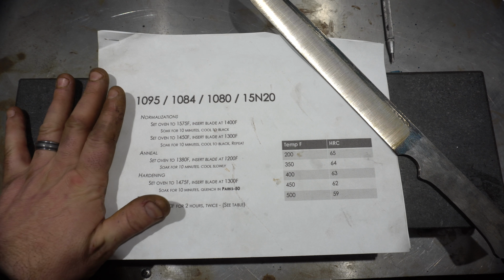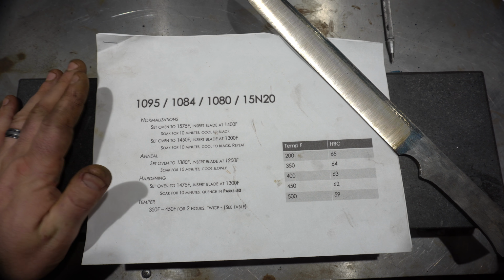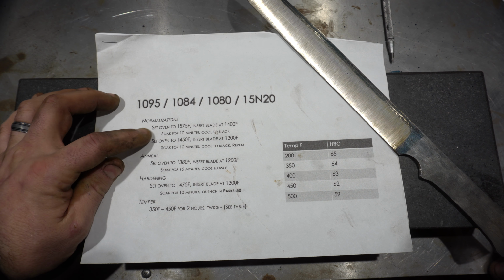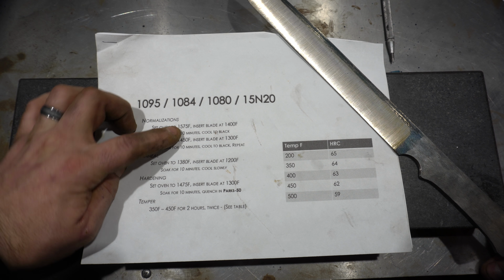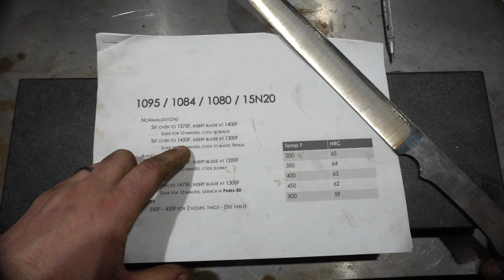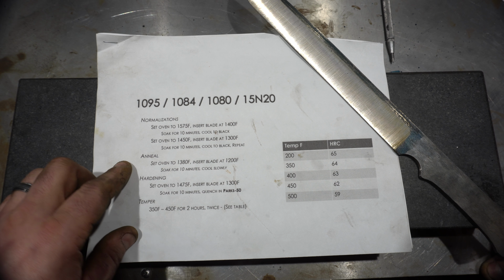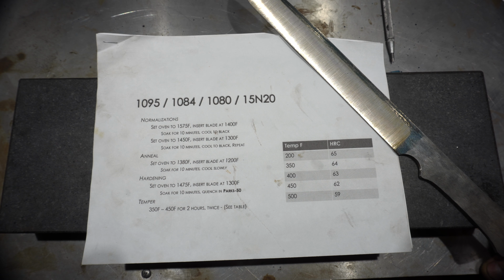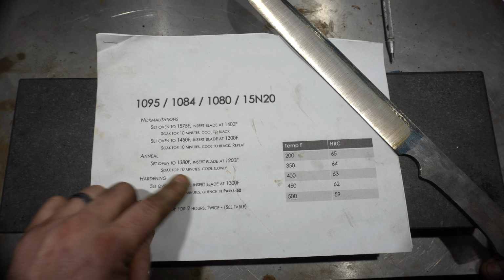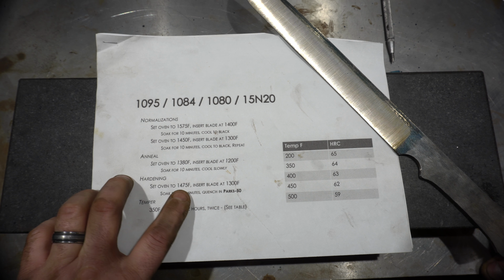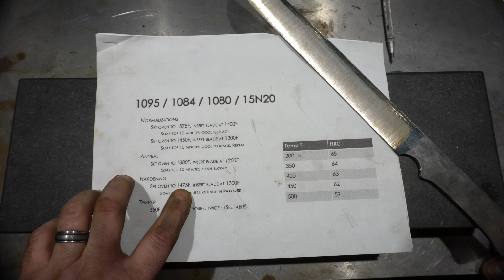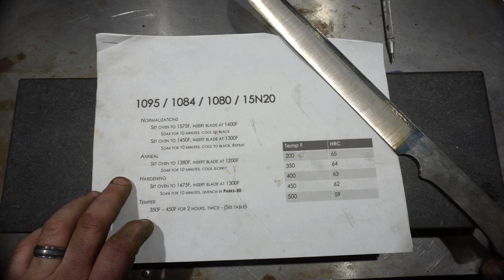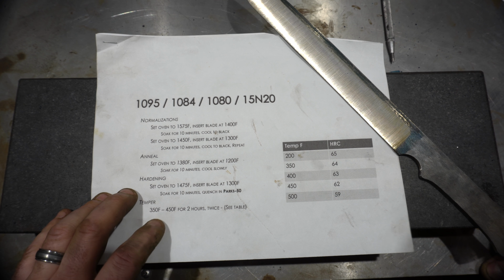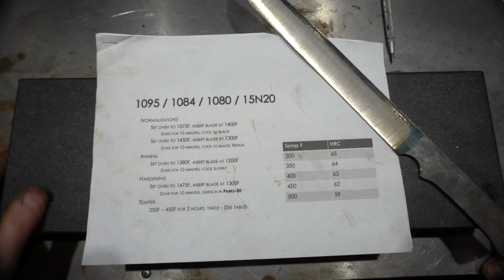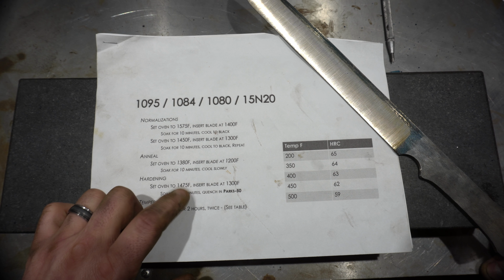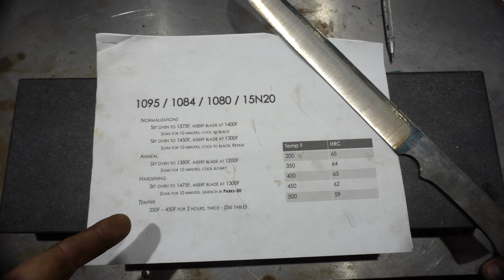So the heat treat for this one is going to be very specific. I'm going to follow all of the steps exactly. So we're going to do the normalization at 1575, then we're going to do 2 cycles at 1450, and then we're going to do a subcritical anneal after those 2 steps. And then we're going to do our hardening, and we say set oven to 1475. I'm actually going to set it a wee bit higher than this. And then we'll check what I'm going to temper it at after I know what the HRC is after this. All right, let's get to it.